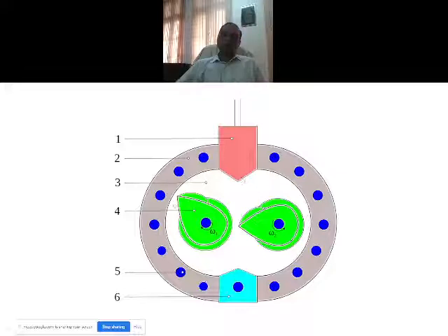Because the mixing time can be very closely controlled and monitored and maintained, batch to batch variation can be minimized. Because the mill cutting or whatever cutting and lateral mixing happening here is happening automatically, and these two are rotating in opposite direction. Now you see there is a small gap here, but as it moves to this side, this portion comes in which has a smaller diameter, so the gap here increases. By the time this comes in here also, this moves in this direction, this moves in this direction.